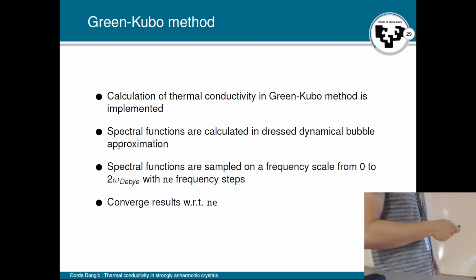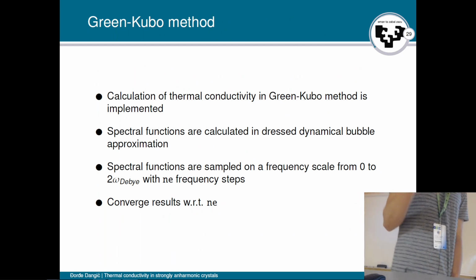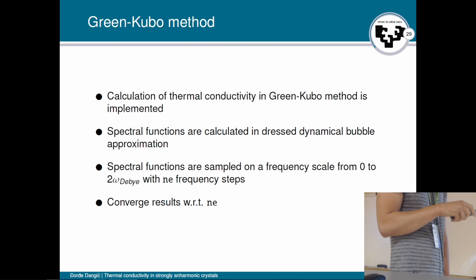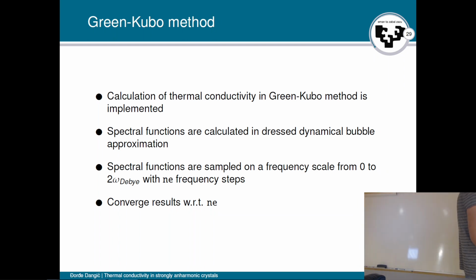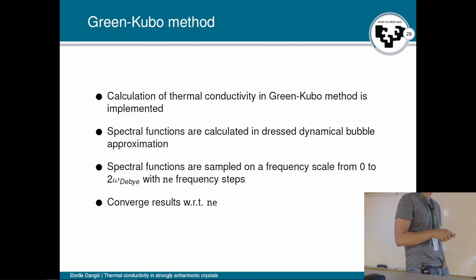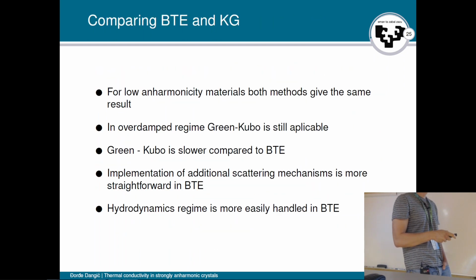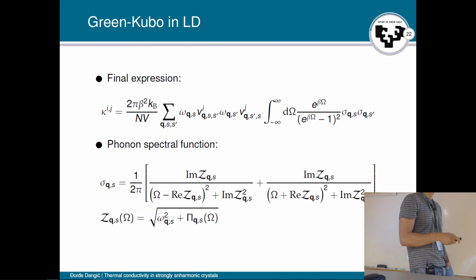In the Green-Kubo method, the calculation is also implemented here. Again, there's no hydrodynamics in this method, so it is equivalent to the relaxation time approximation solution of the Boltzmann transport equation. The spectral function at this point is calculated in the dressed dynamical bubble approximation, so you don't have the 4th order scattering yet. And the spectral functions are sampled on a frequency space, so we have to solve this integral numerically.